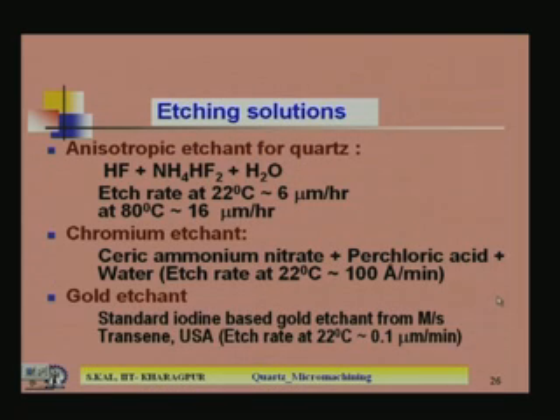Now, here what are the etching solutions that use NH4HF2. So, the HF we take some amount, then NH4HF2, the ammonium fluoride, plus H2O, and the etch rate has been found at 22 degree centigrade, means room temperature, to be 6 micrometer per hour, and if you do the same etching at 80 degree centigrade, it is 16 micrometer per hour. So, that means automatically room temperature etching is very slow.